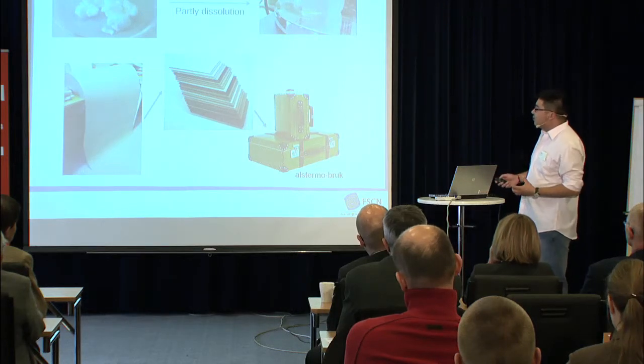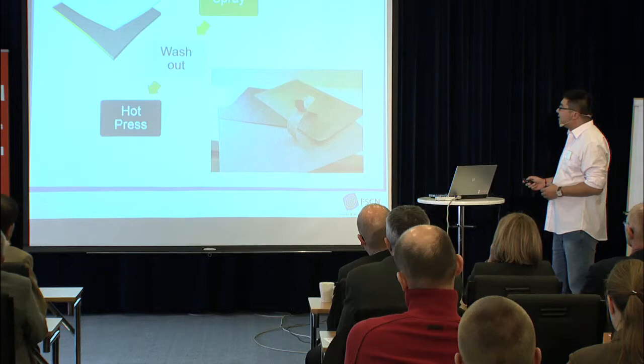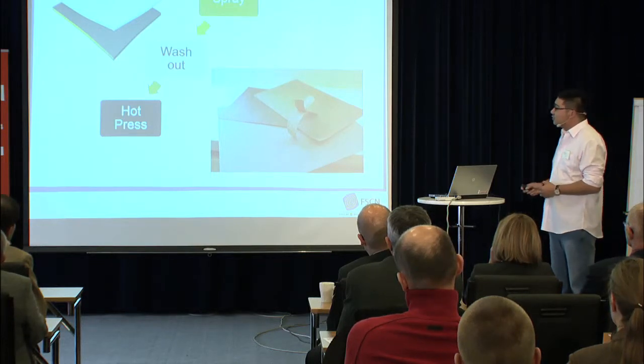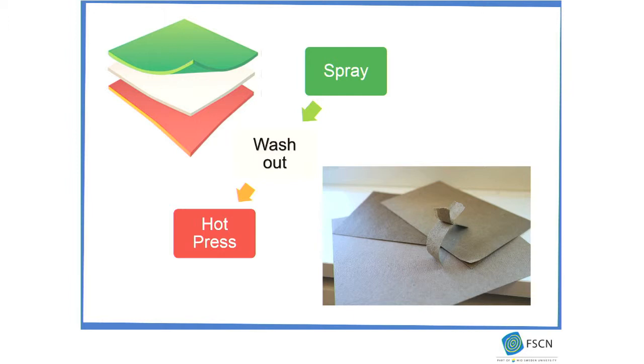So we have the ideas and we have a few trials for those. At the beginning, we have this kind of process to produce laminated paper. We spray each piece of the liner board and then we laminate them together and wash out the excess amount of sodium hydroxide and urea. We hot press it to regenerate the cellulose and then we achieve this kind of quite tough materials. But with this method, there's a problem: it's not that easy to control and repeat the result, because it's very hard to make sure we have exactly the same amount of chemicals absorbed in the materials or that we wash them under the same condition. So we came up with this kind of method.